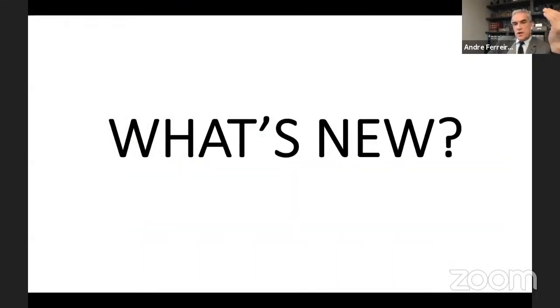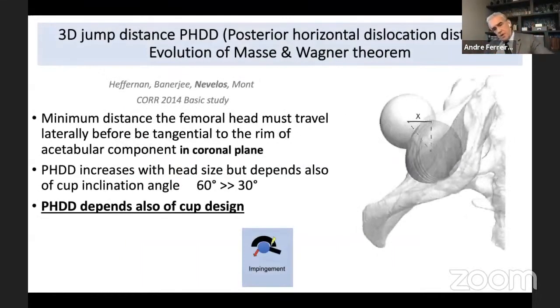But what is new now about dual mobility? We have to refer to the work of Nevelos. Remember that I explained to you that when we increase the jump distance only on the frontal plane, described by Masse and Wagner, there is a decrease of instability. That's right, but of course, we have to consider it in 3D. And the posterior horizontal dislocation distance described by Nevelos is more important because it is the distance for the dislocation to the posterior part of the joint, or the anterior one in case of anterior approach, of course.